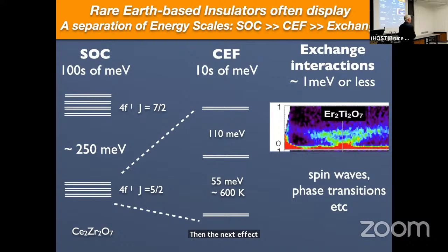And the crystal field effects are due to the fact that the cerium ion is not in a vacuum, it's not in outer space, it's sitting in this solid, and 2 or 3 angstroms away, there are these electronegative oxygen ions. So the electric field at the position of the cerium is 0, but the electric field gradients are very large, okay? And those effects are strong enough to take the 6 states, so this is J equals 5/2, so there's 2J plus 1 fold degenerate. So there's 6 states, and it'll split them up into 3 sets of doublets. And those will be separated by about 50 meV each, okay?